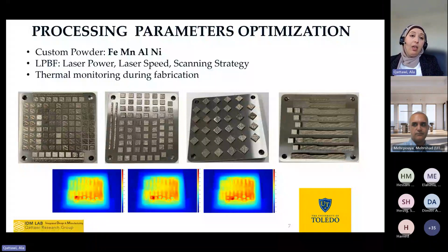And once the laser passes, there's a significant thermal reduction or thermal energy loss from the powder or the component to the plate. All this dynamics of the thermal energy is causing different problems in the production. So what we introduced is in-situ heating. During the whole build, we have a heat-assisted process. The building plate will stay at 500 or 600 C while we're printing, and that's what reduces the residual stresses, reduces the thermal inconsistency across the building plate, and significantly improves the quality of the parts that we're actually producing.